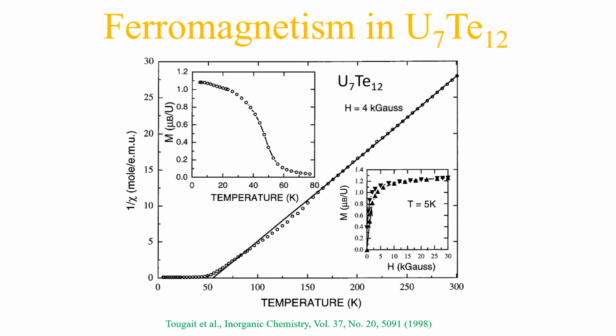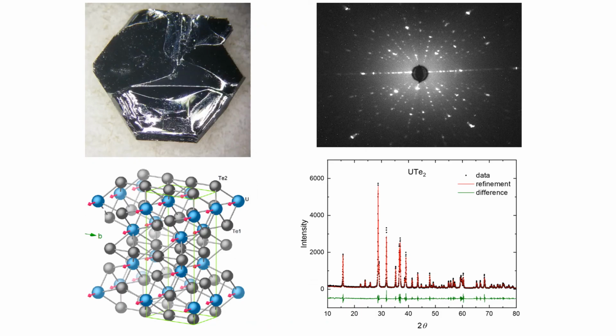This is certainly doable. We tried different compounds. At this time, our target was uranium-7, tellurium-12. It is a ferromagnetic compound with Curie temperature at 50 K. The idea was to synthesize this compound, then apply pressure or do chemical substitution to see if it superconducts. Unfortunately, I kept getting a different compound, uranium-tellurium-2.